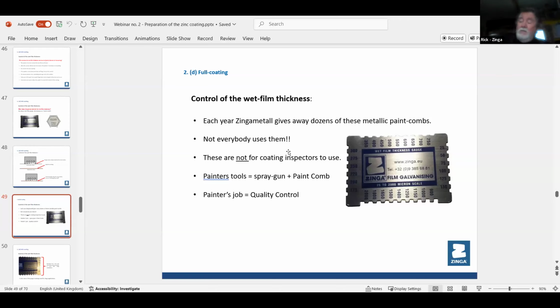You should be doing 2 passes. If you're starting the job, you do 2 passes, measure, okay, clean it, measure again, measure again. If it looks okay, 2 passes. The entire beam is 2 passes. But if you measure 2 or 3 measurements, it's a bit low. Give it 1 more pass of the gun, measure again. It looks okay. The entire beam gets 3 passes of the gun. That's how you use a wet film gauge.